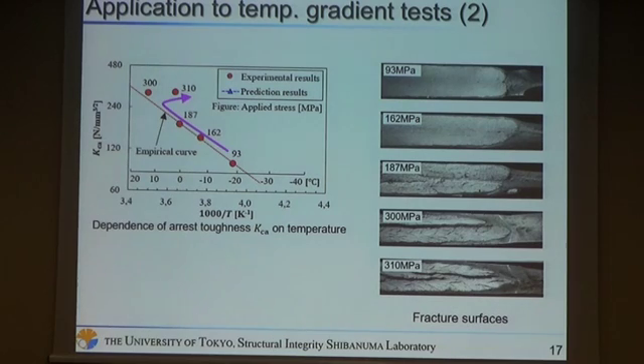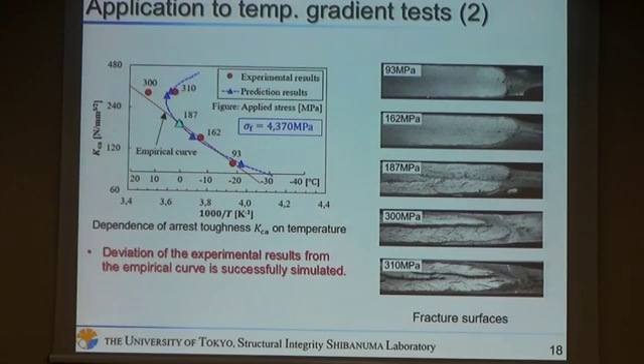In addition, these photos show the fractured surfaces obtained in the experiments. We can see that the higher applied stress makes a deeper side ligament like this. To simulate the test results, we identify the fracture stress like this. And the prediction results of the relationship between KCA and temperature are shown on this graph. You can see that the deviation of the experimental result from the empirical curve is successfully simulated by the proposed model.